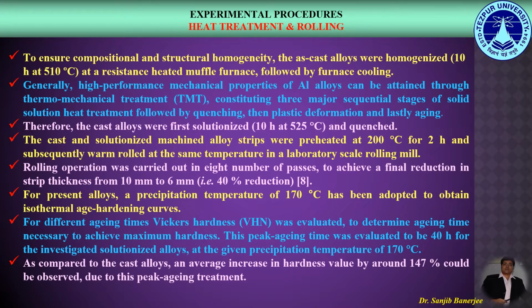After casting, the alloys were processed by standard thermomechanical treatment or TMT. Therefore, the alloys were first solutionized at 525 degrees centigrade. Then they were warm rolled at 200 degrees centigrade. And lastly, the alloys were age hardened at a precipitation temperature of 170 degrees centigrade for 40 hours because the peak aging time was evaluated to be 40 hours for the investigated solutionized alloys.